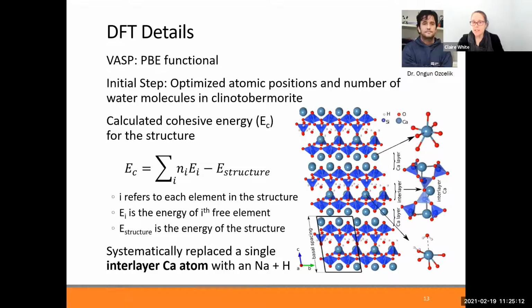So here's some details of the DFT calculations. We use VASP, and particularly the well-known PBE functional. The initial thing we did was to optimize the structure of clinotobermorite, including water molecules in the structure, because that was unknown in terms of having an accurate structure. And then what we did for every single structure we